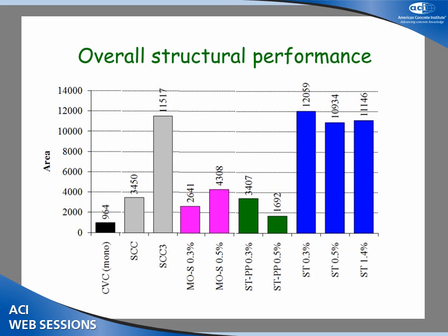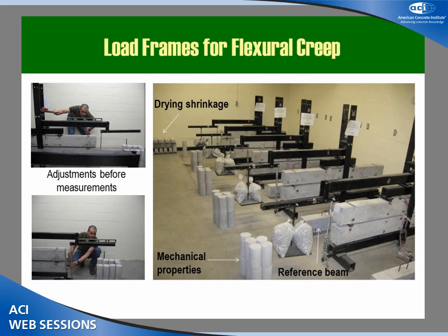Similar to adding another bar in the tension zone, which made it more congested, but that's giving similar results. In terms of structural performance, the use of the synthetic fibers also improved the performance, but not as much as the steel fibers.